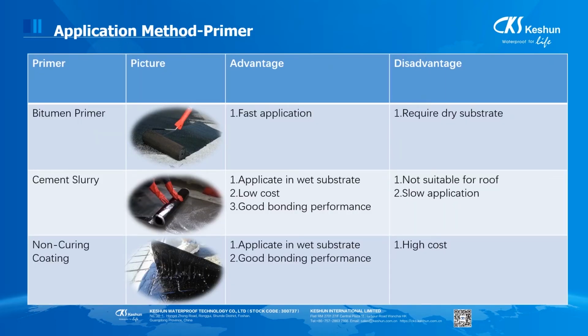The most common one is using bitumen primer. It is fast, cheap, and easy to apply. But if your construction site is raining a lot, you cannot wait for the substrate to be fully dry. You can use cement slurry as primer. Or if your project has budget, you can choose non-curing coating with APF-3000 to make it a 2-layer waterproofing system.